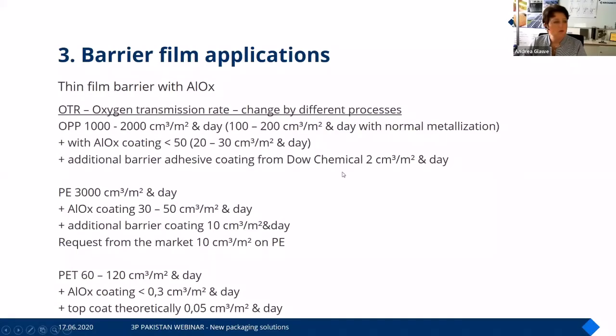Here you have some ideas of what is already possible on the market. So you see, for instance, OPP has a very high rate for letting moisture and oxygen in. And with only AlOx coating, you can already reduce the value to only 50 cubic centimeters per square meter a day. And with an additional wet coated barrier, which is, for instance, supplied by Dow Chemical, you can go to a much deeper value. So the combination of aluminium oxide and an additional coating, this is what we are looking at when we speak about the aluminium oxide business. Here you have some other values.